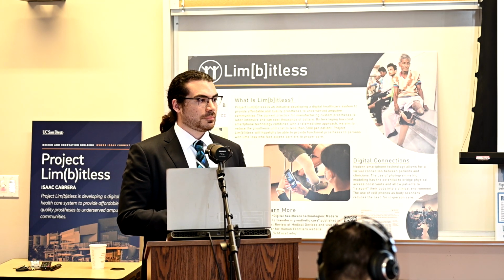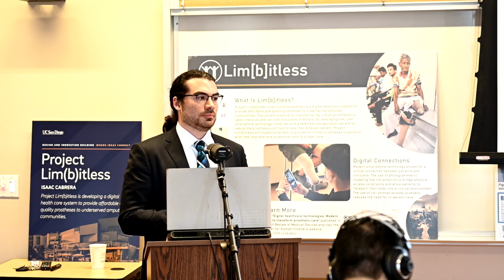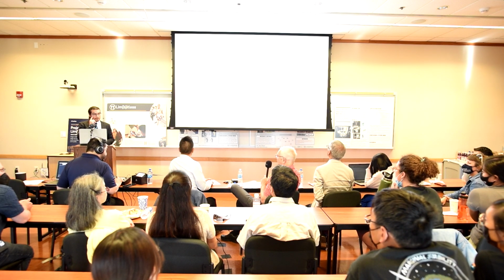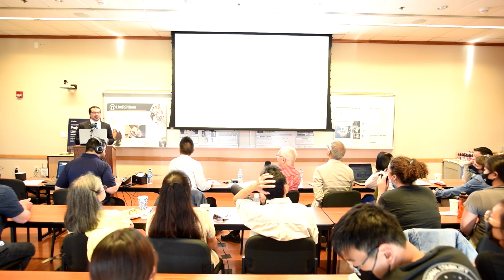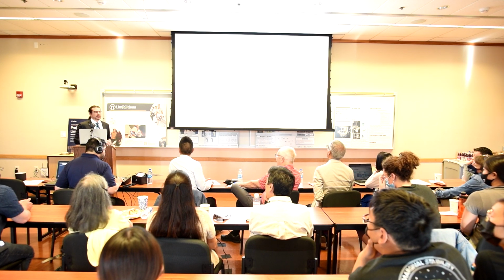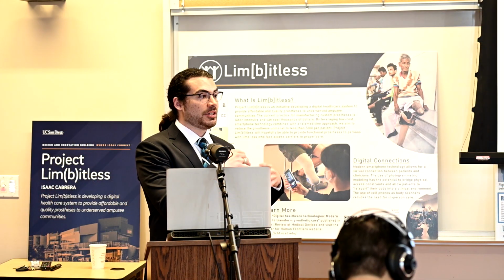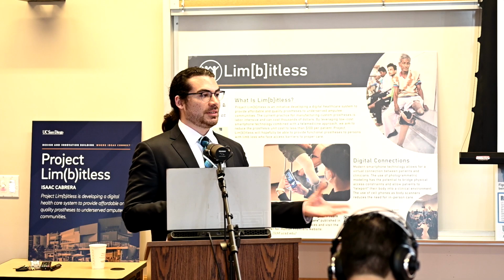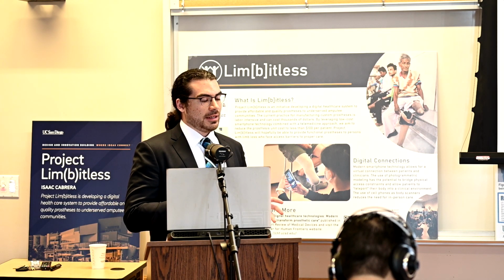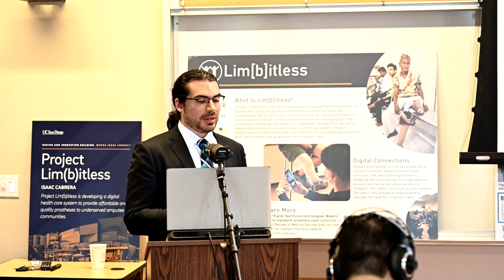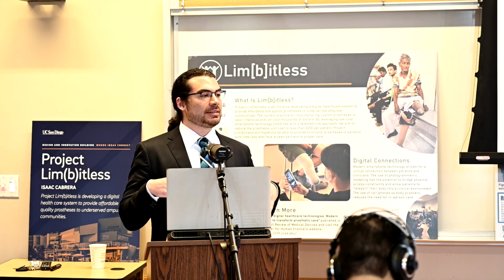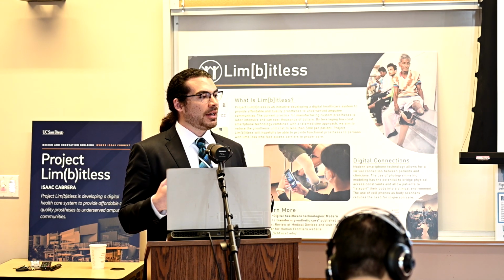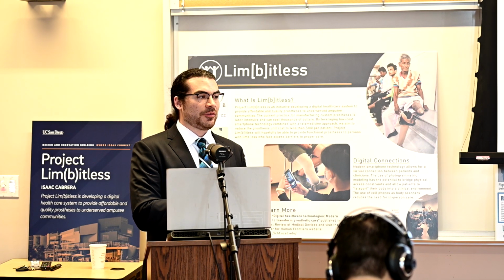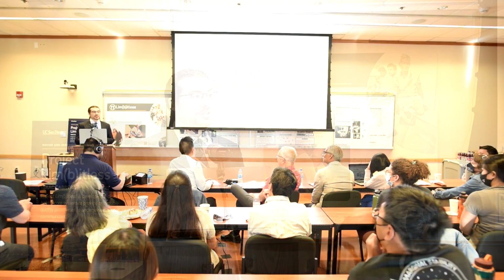So one more important parameter, and that is the environment and the environmental temperatures. Yeah, because if you go in the snow or in the desert, then these material properties change under these extreme conditions. Yeah, that's where the carbon fiber PETG specifically is really one of the more robust to environmental conditions, versus your standard PLA, which has tons of environmental degradation. And so it's really not meant and should not be used for this purpose. But for me, it was an effective control because there's a lot of literature, so I could see if the mechanisms that I was interested in improving held true for controls. But you're right, they're really not suitable. But the urethane PETG composites really could be used, because they're highly resistant.